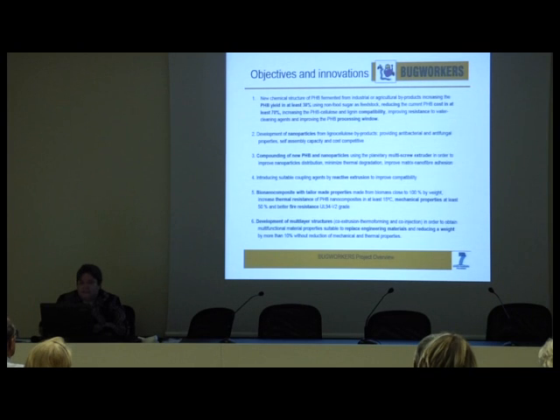We want to increase the yield of the PHB production by at least 30%. We want to reduce the cost by at least 70%, and with the studies we did previous to submitting the project, with the people working both in the sugar production and in the PHB production, we believe that we will reach this 70% decrease in the cost. And we also need to increase the processing window for PHB. So these two ways of obtaining the homopolymer and the copolymer, and then to obtain blends to fit the needs of the different applications, we believe are the route to obtain this increase in the processing window.